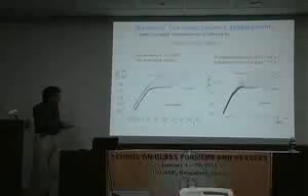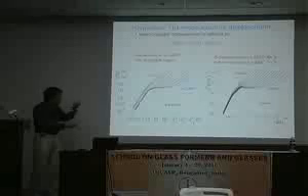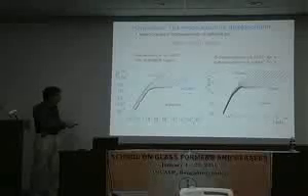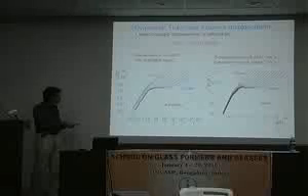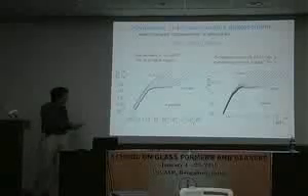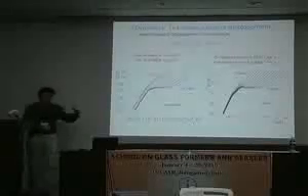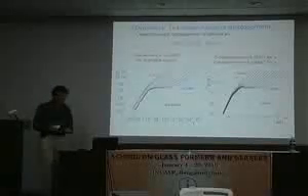From the density of states, for example, you would be able to calculate analytically, I mean, with a computer, but in principle it's an exact expression, the behavior of the system up to this plateau here, that is to say, you would be able to calculate all these bumps, etc. It's the same type of information, because up to this time scale here, on the blue line, the system does not know that actually it can flow if it's patient enough. Okay, yes?